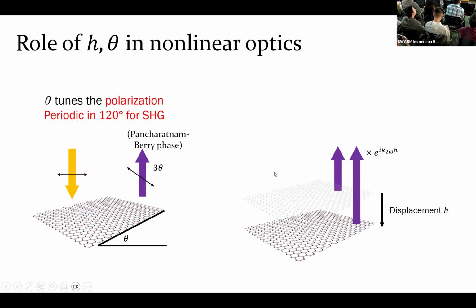And now we can also think about the other degree of freedom that we have in the system, which is controlling the displacement between the two 2D materials, right? And that's what we call displacement H. And this one is simple because as you change the distance, you basically change the relative optical phase between the light that comes from the first layer and the light from the second layer, just by a phase factor that is proportional to the wave vector of the light. So now what if we use this theta, the twist angle, and the displacement H in conjunction? I just tune them together because these are the knobs we have in this system.